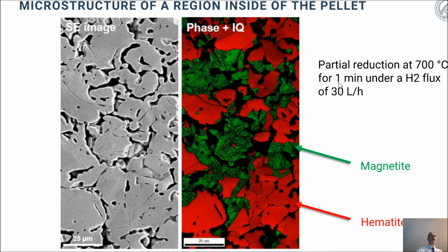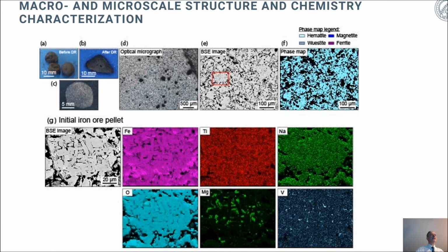And you see here specifically after 1 minute exposure to pure hydrogen at 700 degrees centigrade, 2 phases. One being the original hematite, so that is the original material from which the pellet was made. And this is the already reduced material into magnetite. So this is the first reduction step, which, as we saw in the beginning, is a very fast reduction step. But you can see really how these 2 phases are intermixed. So there's no global huge growth front that goes through the pellet from the outside to the center alone, but you have also inside each of these near surface or near center regions a very complex interplay of the geometry and the local reduction kinetics. Now let's look at this a little bit more in detail, because there are not only structure features, but there are also chemical features that you inherit.